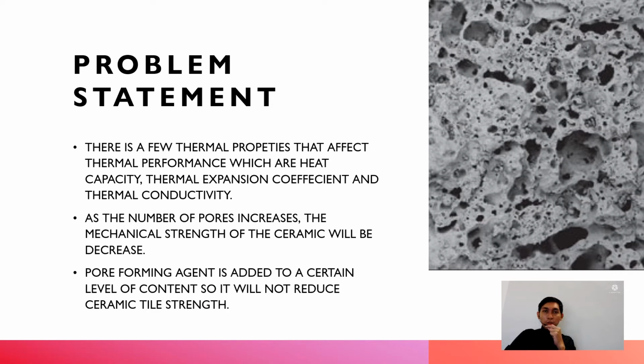Okay, now let's continue on the problem statement. There are a few thermal properties that affect thermal performance, which are heat capacity, thermal expansion coefficient, and thermal conductivity. As the number of pores increases, the mechanical strength of the ceramic will decrease. Pore forming agent is added to a certain level of content, so it will not reduce ceramic tile strength. As you can see, on the right part of the slide, there is a picture of the porous ceramic tiles using the scanning electron microscope.